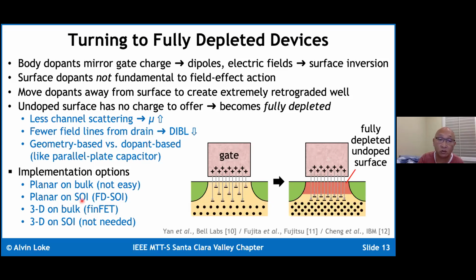You can have planar on SOI, which is FD-SOI. Sometimes it's called extremely thin SOI or ultra thin body and box SOI, where the idea is that this fully depleted undoped surface, you replace with a sandwich stack of an SOI layer, followed by a buried oxide layer underneath. And so fundamentally, the substrate makes it much easier to create a fully depleted undoped layer compared to planar on bulk. You can also have 3D on bulk, which is essentially a FinFET, or you can have FinFETs on, say, SOI. Turns out that you don't need this, and so the industry has stayed with 3D on bulk.